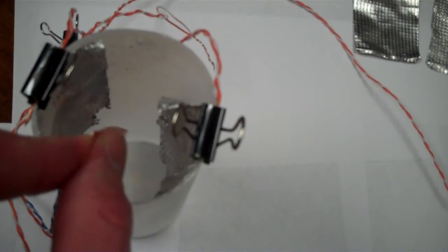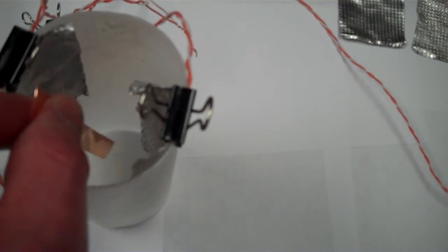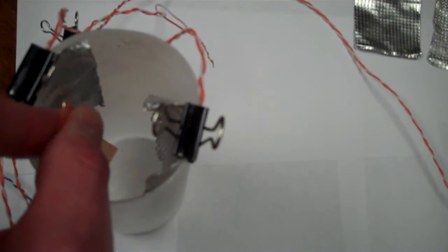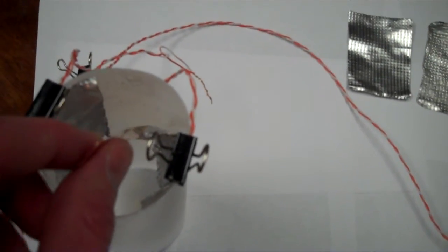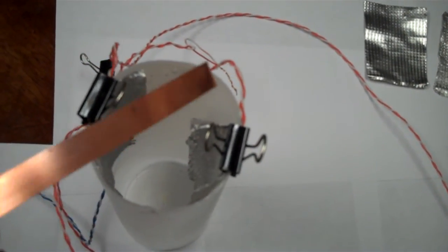If I only had one piece of indium, only one indium anode, it would only really plate on the side of the copper strip that's facing that anode. It's pretty much a line of sight plating process.